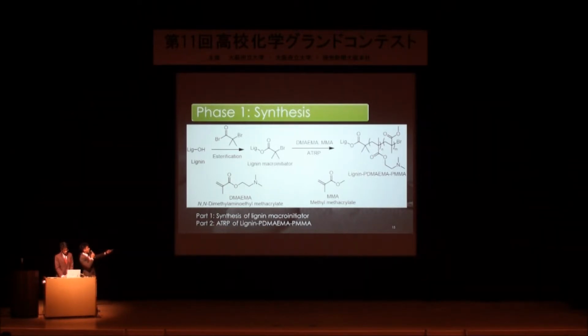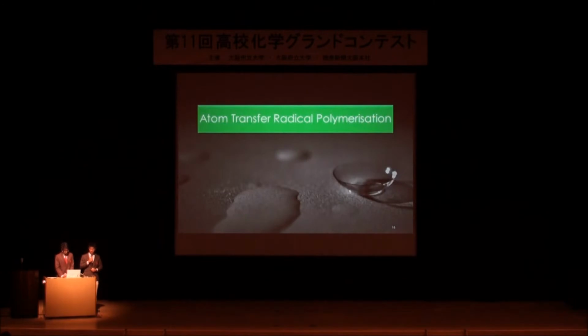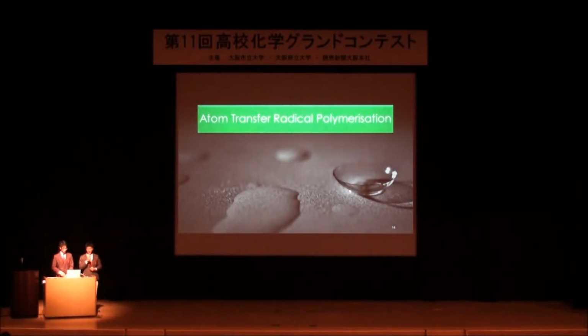will be polymerizing DMA-EMA monomer, which has this structure here, as well as MMA monomer with this structure here, onto the lignin macroinitiator. This is done by an ATRP reaction, and it produces lignin, poly-DMA-EMA, poly-MMA. So what is ATRP, you may ask?